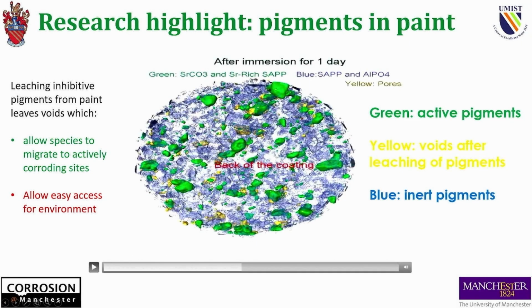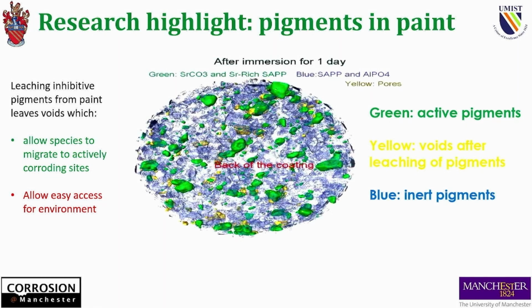After one day, we've taken away the organic coating components, and we're left with the green bits, which are the active inhibitors, and the yellow bits, which are the voids where the active inhibitors have dissolved. If you think about it, if it's going to dissolve, of course it's going to leave a void, a measurable void. What happens to the paint with these measurable voids?